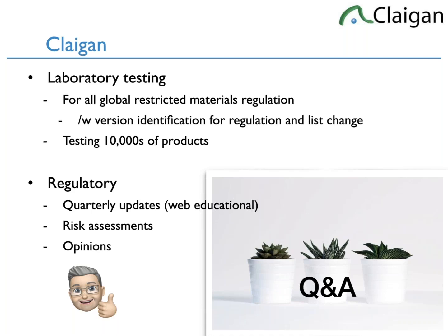And the bigger one is lead in aluminum at 0.4% is changing. Lead in cast aluminum, so molded aluminum, will continue at 0.3%, which is not really a big difference, actually. But machined aluminum, so machined aluminum is CNC machined or rolled or extruded or forged. That's all machined aluminum. They will no longer be allowed roughly by mid-2024. Lead in aluminum: cast aluminum will be allowed. Lead in aluminum: machined aluminum will not.